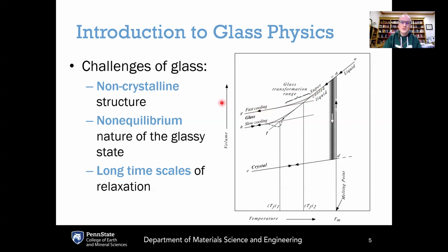And so some of the key features of the glass, because of this glass transformation or glass transition, is that glass has a non-crystalline structure. It doesn't have this well-ordered structure like you get in a crystal. Instead, it has a structure that is much more similar to that of the liquid. Also, glass has fallen out of equilibrium, so it is a non-equilibrium state, which means we can't use the same equilibrium physics to describe the structure and the properties of glass. And because of its really high viscosity, there are long time scales associated with the flow of glass, the so-called relaxation behavior of glass, as it gradually tries to go back to its metastable supercooled liquid state.